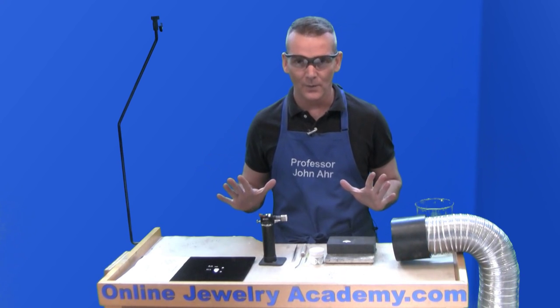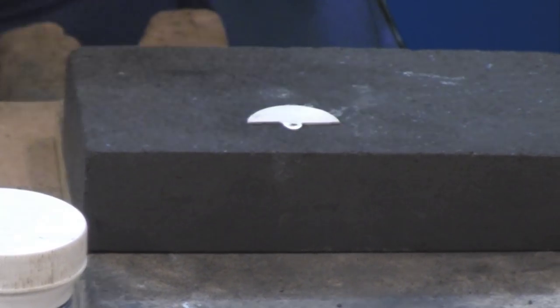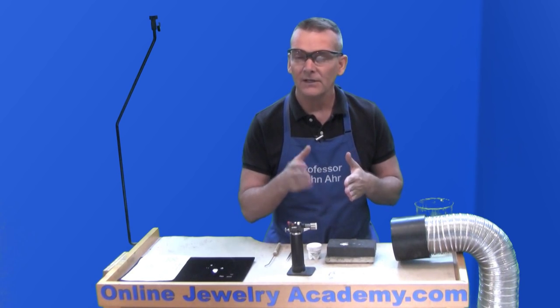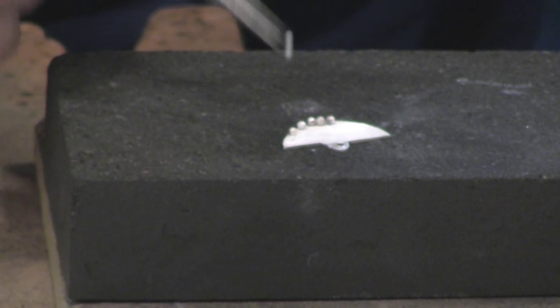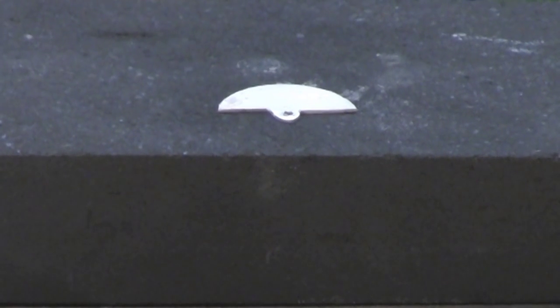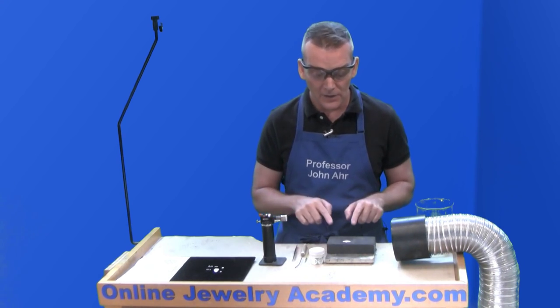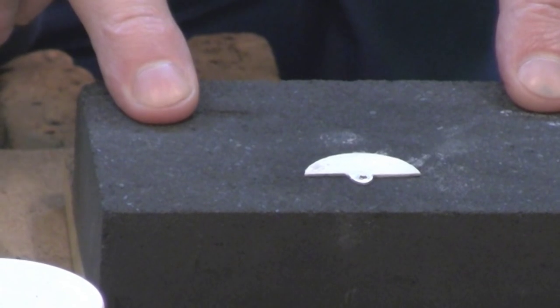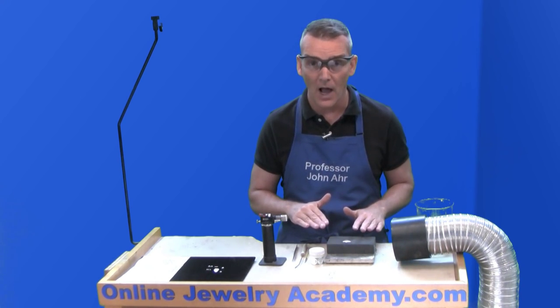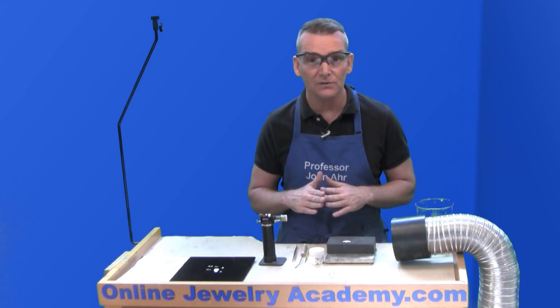The secret to success with this is to pre-paint your flux onto your piece — the base piece — and allow it to dry. If you're having trouble keeping the little balls in place, you can cheat a little and add just a touch of flux to the bottom of them to hold them in place, but you do need to dry that flux out before you begin. You can actually preheat the piece if you want to. The flatness of the block is important because we don't want the piece slumping, moving, or bending out of shape as we fuse the balls onto it.